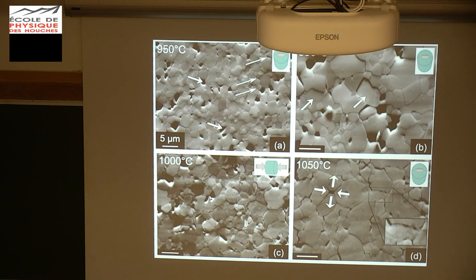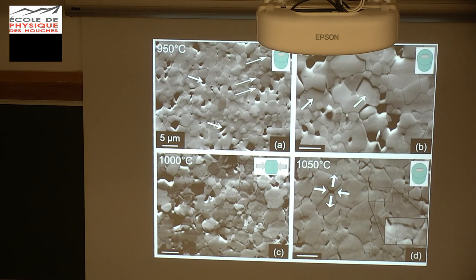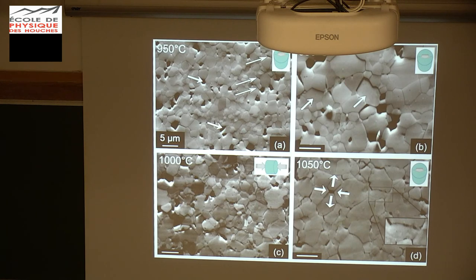We decided to go back to basics and really spend more time looking at the samples. Something is not showing up in the MTEX treatments of basic EBSD, but I want you to have a closer look. These are the same images from the lowest to the highest temperature. You have some pluck-outs of course, but what we also see is gaps opening — not all of them are pluck-outs. Zooming in, you start to see this sort of out-of-plane displacement that we actually see everywhere. The grain boundaries remain very nice. We increase temperature and the microstructure changes a little bit.